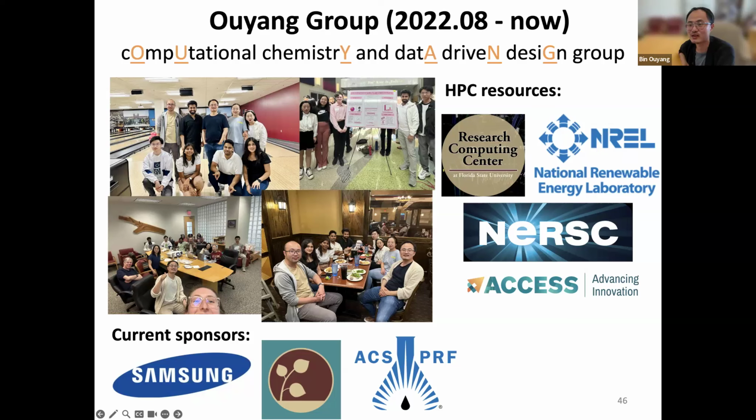Plus U is sometimes a little sketchy, system dependent, and an empirical fitting parameter which deviates from the idea of first principles. So r2SCAN can really reproduce, at least in the systems we care about, the formation energy. So part of our databases are built on r2SCAN as well.